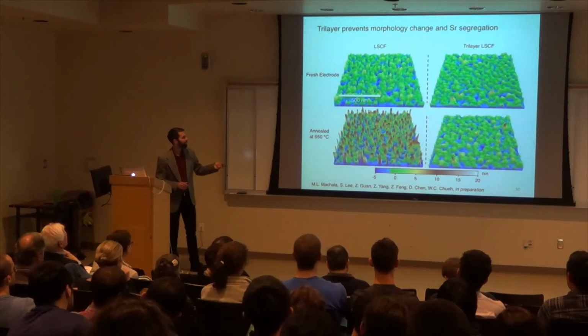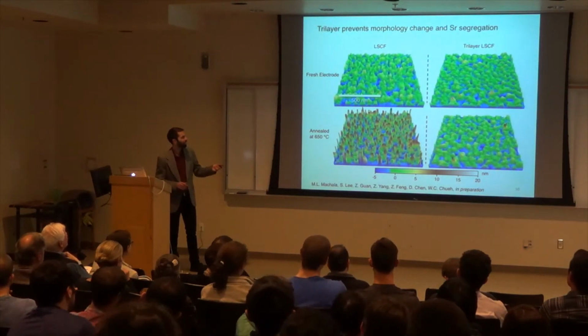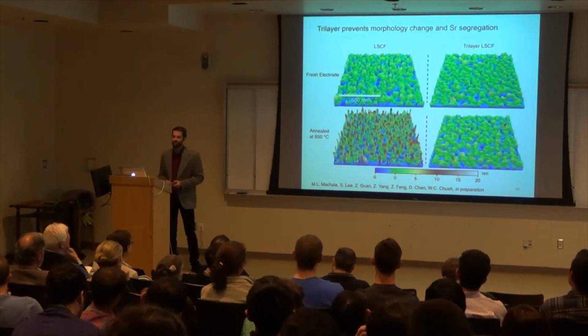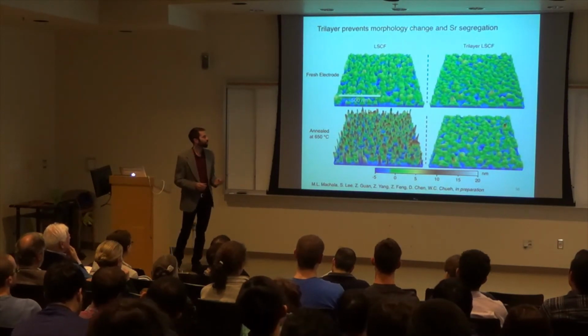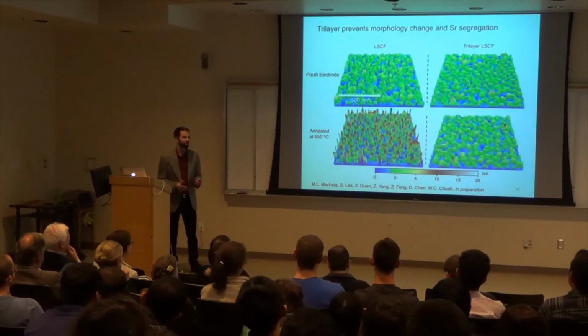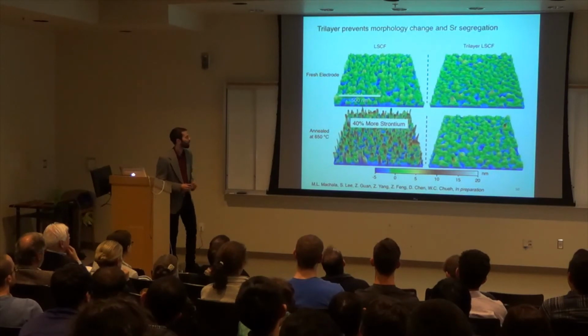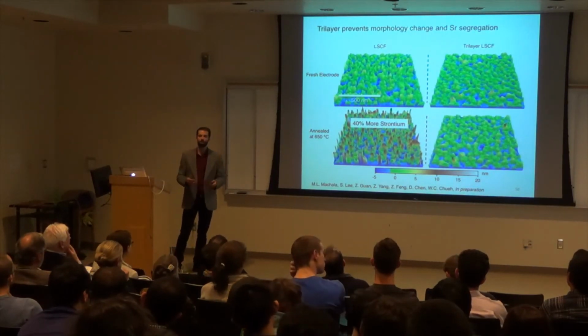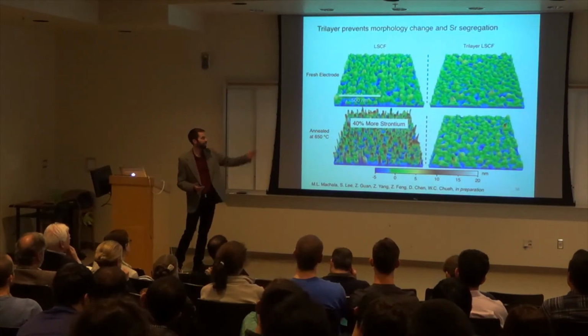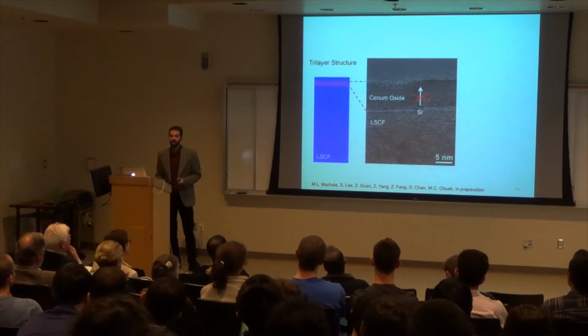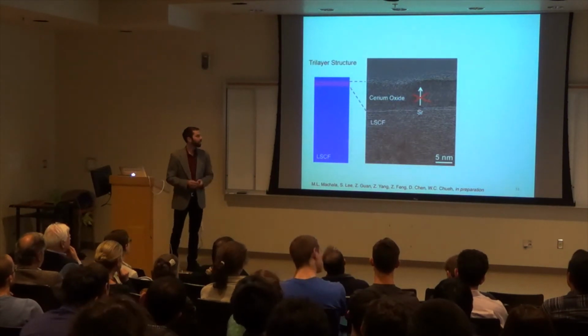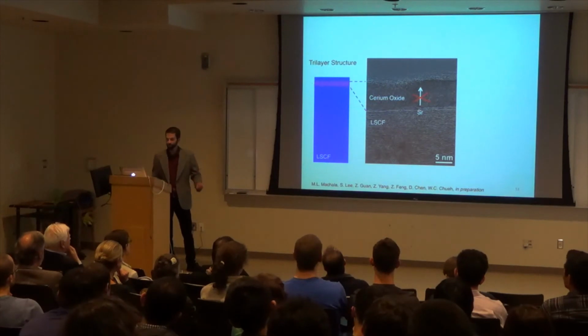And this tells us that there are a bunch of precipitates on the LSCF here, but the trilayer structure doesn't change at all. And then when we take this to the synchrotron to do chemical analysis of the surface under the same conditions, we see that the surface is actually about 40% enriched in strontium compared to the trilayer structure. So what we can say is that this is effectively blocking the strontium from getting to the surface.